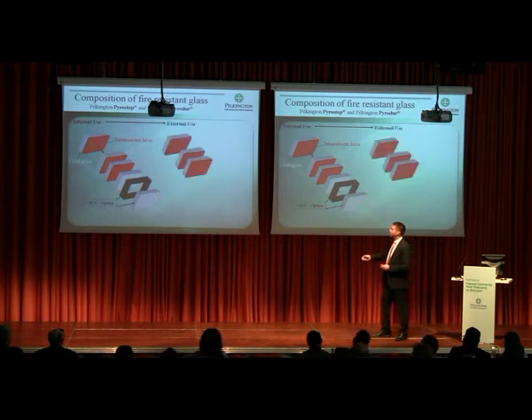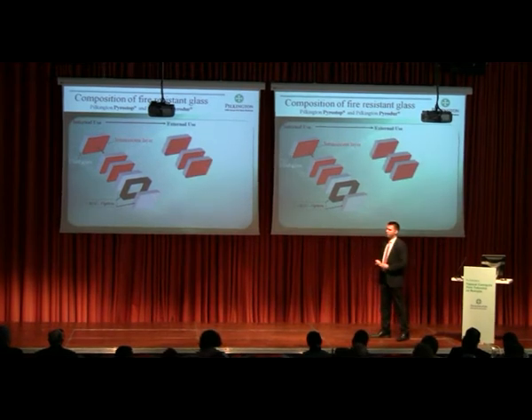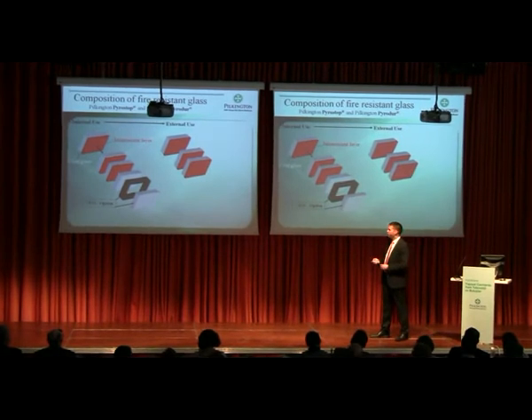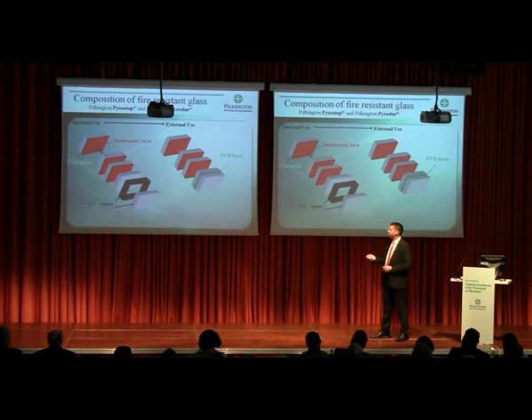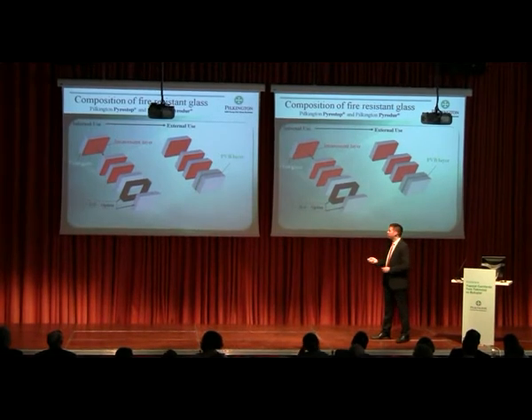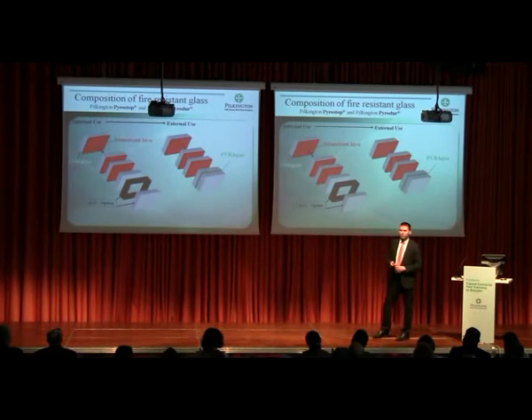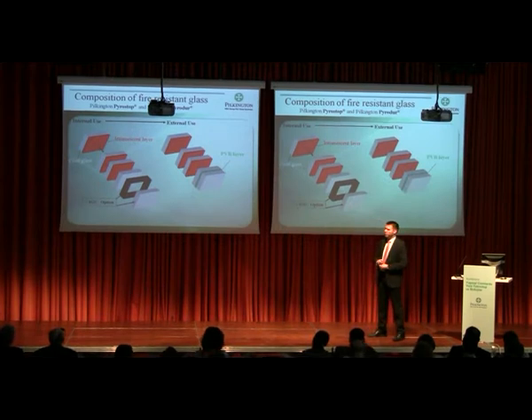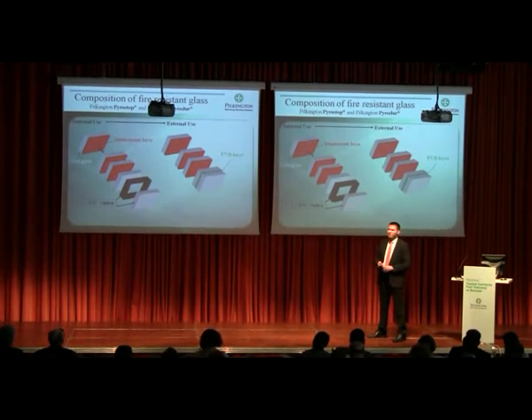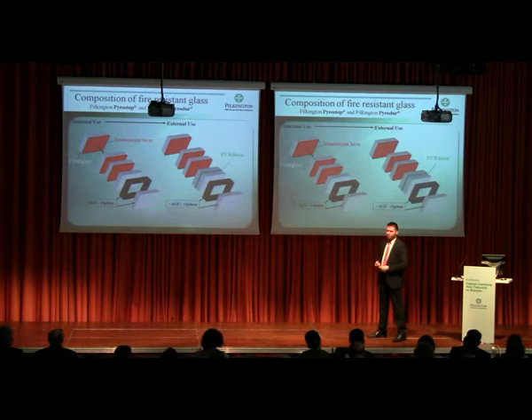We distinguish internal applications and external facade applications. The composition actually is the same. There is only a minor but a very important difference. We include a laminated glass into that composition to protect our interlayers from UV radiation. So if we have fire protection glass installed in a facade and if it is exposed to sunlight, for example, then we need to protect the interlayers from the UV radiation. And therefore, we incorporate a PVB layer which absorbs the UV radiation. Again, double glass units, of course, possible. Externally and facade application, of course, usual.